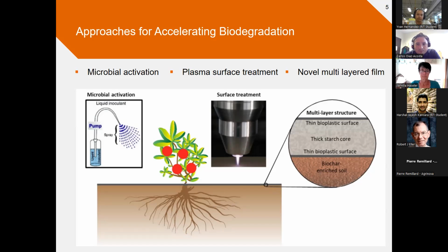The third approach, which requires us to rethink a new film structure, is this: instead of having these polyesters that degrade slowly, and we know it, why don't we minimize the use of the polyester by creating a sandwich structure? So we have 2 skins made of polyester and a core made of starch. And why starch? Because the starch is food for microbes mainly. So in doing that, we are addressing the biodegradability and also the cost, because we're not putting this expensive polyester in the whole structure. Now we're maybe using 10% of that in the skin layers.